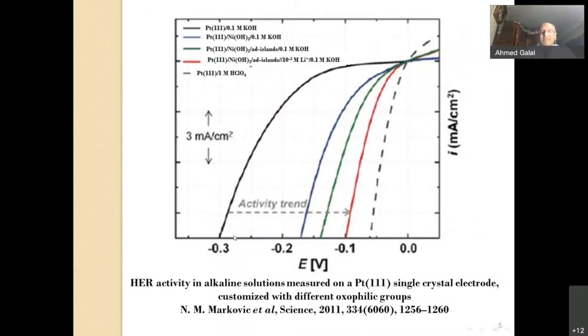In some of the publications that have been coming out is the enhancement of the surface of platinum, especially single crystal ones, and for this purpose, the enhancement using transition metals and other oxophilic kind of ions would enhance the activity of hydrogen evolution, and the activity increases as the surface of the platinum is being modified, once by nickel and once by introducing something like lithium ions. So the introduction of some extrinsic materials over the surface will not lead to the so-called poisoning of the surface, but on the contrary, will just enhance the performance by reducing first the overpotential needed for the hydrogen evolution and increasing the current density at a certain given potential.